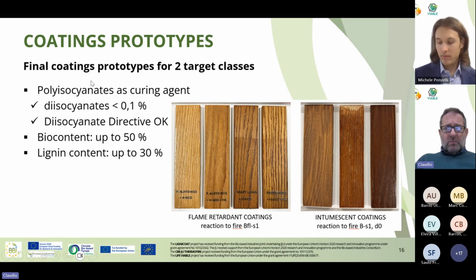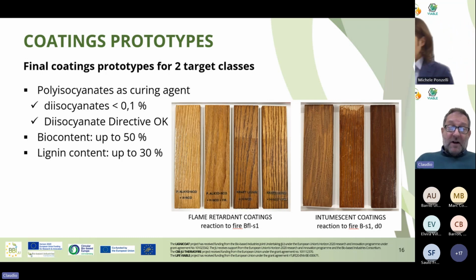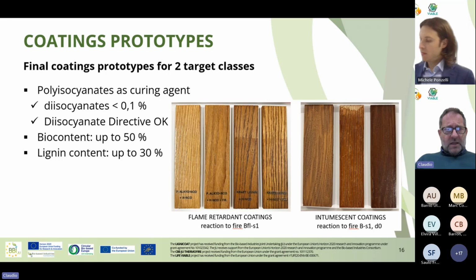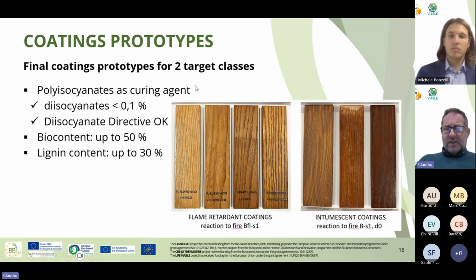But there's good news. The isocyanates that we are using and that most paint companies are using nowadays are large molecules, polymers or adducts with a high molecular weight. And these are not as dangerous as the small molecular weights. The materials that we use have a diisocyanate content lower than 0.1% that allows us to classify them as less dangerous in terms of labeling, REACH, CLP, and the diisocyanate directives. So all in all, these products are relatively environmentally safe and safe from the perspective of health at the workplace.